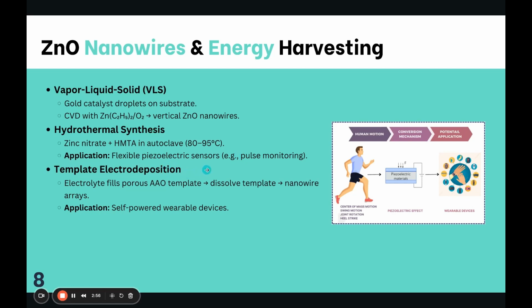Then comes template electrodeposition. The template is a porous anodized aluminum oxide membrane with nanoscale pores. The electrolyte contains metal ions such as zinc ions. An electric current drives metal ion reduction at the template's pores. Nanowires form inside the pores as the metal deposits. The template is chemically dissolved, leaving behind freestanding nanowire arrays.